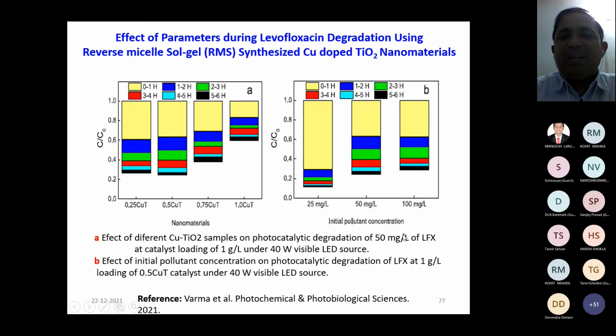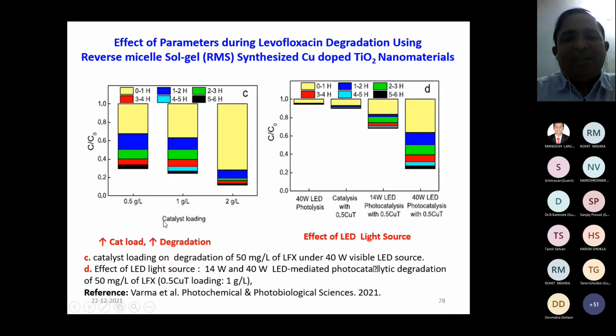Then for initial pollutant concentration we checked 25 ppm, 50 ppm and 100 ppm. We observed the same trend that we discussed. Then we examined catalyst loading. Again, as loading is increased, degradation is improved, in the range of 0.5 gram per liter to 2 gram per liter. And for the effect of light source, we used two types of light source, a 14 watt LED light source and a 40 watt LED light source. We observed that as LED intensity is increased, photocatalytic activity also increases, and we ensured that this is because of the photocatalyst, not because of light, and for that we also ran photolysis. It is in the reported paper, and this paper has just been accepted and is in press, and maybe in 1 month it will be available in open literature.